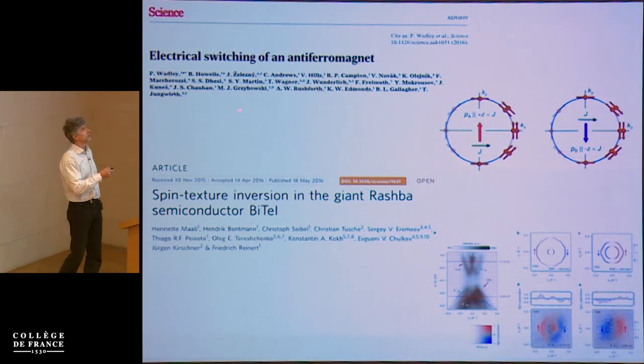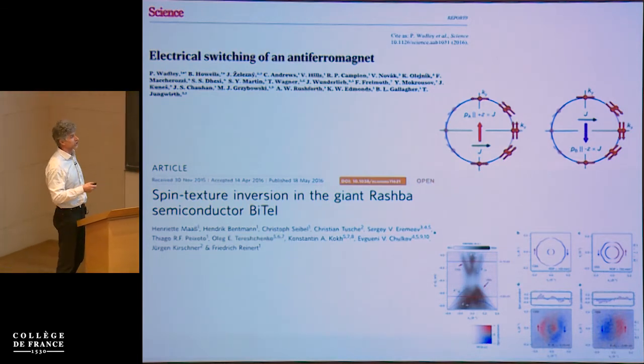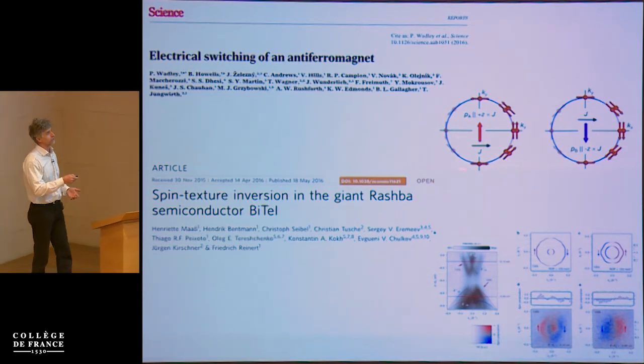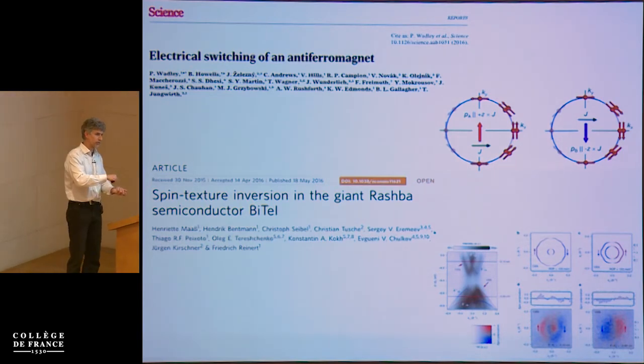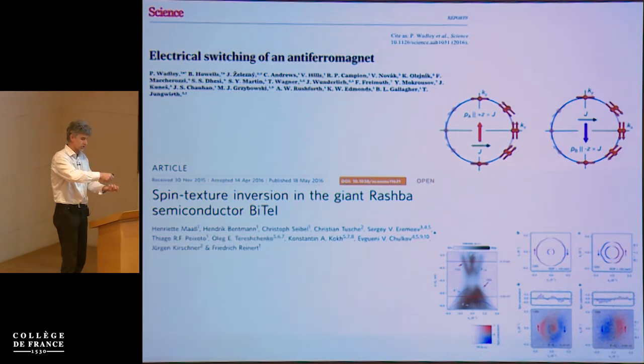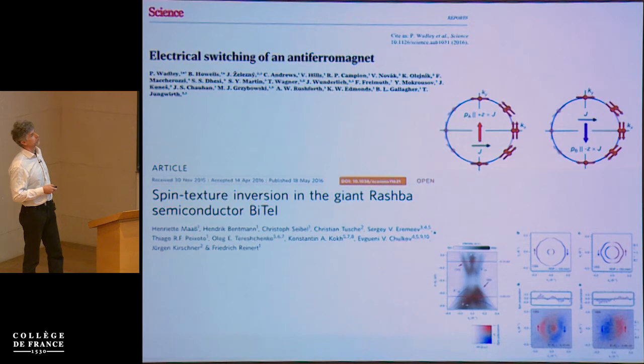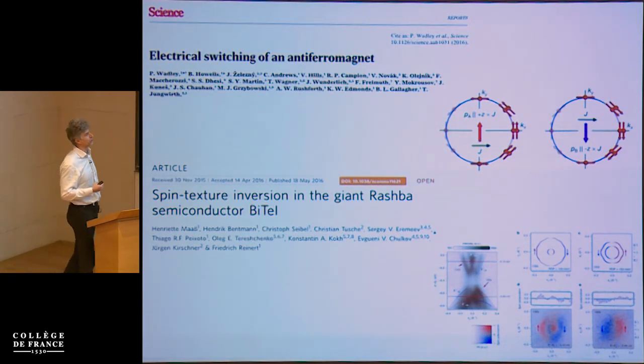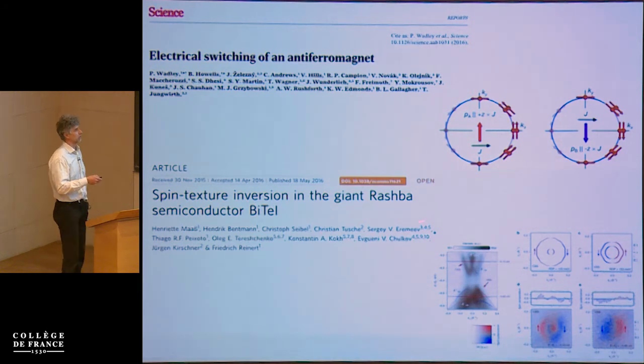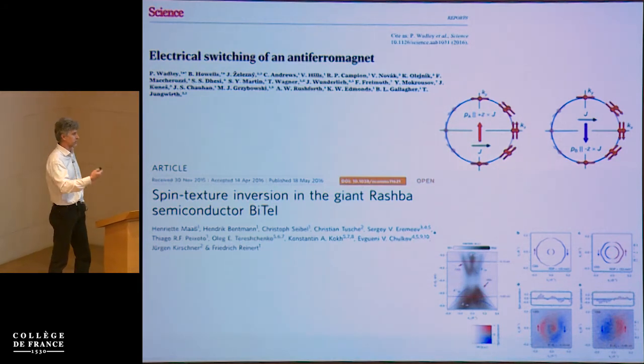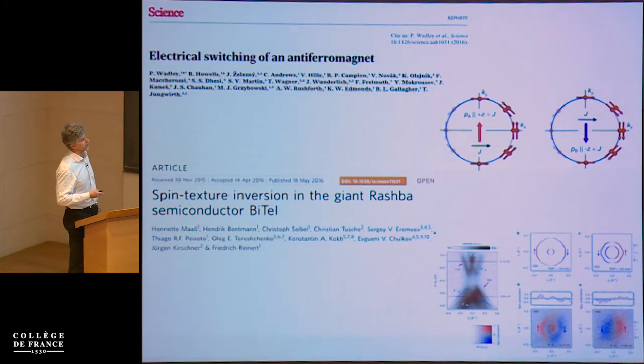Nevertheless, it is interesting to look at other materials, or what one can do with such spin textures. For example, spin textures generated by spin orbit coupling have recently been used to manipulate antiferromagnets and switch the magnetic orientation, the null vector of an antiferromagnet, by applying a spin current. This is, however, in the realm of non-equilibrium physics, and is in general a very hot topic in the field of Rashba semiconductors with strong Rashba spin orbit coupling.